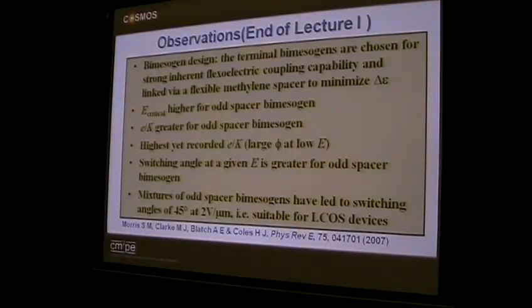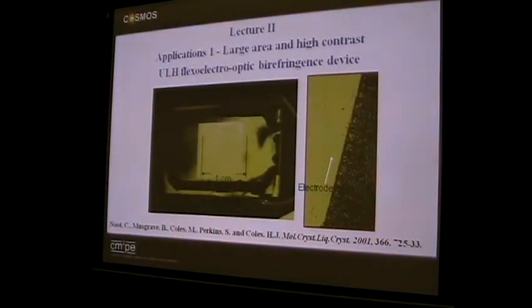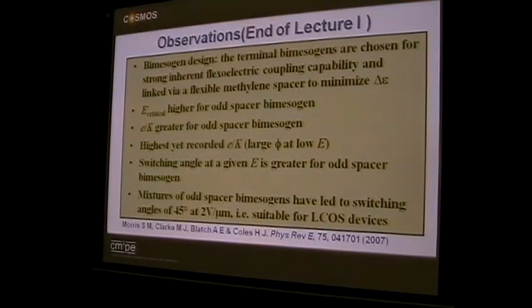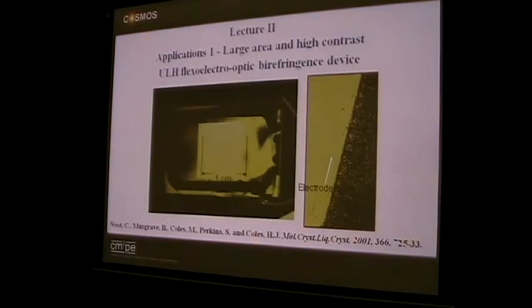Some of the device geometries that are important for what I'm talking about. Firstly, what I want to do is follow on with how you make a device. I said you align the helix in a plane and then you rotate the optic axis. So if I look at an aligned sample, this is the electrode edge here, about a centimeter square, and you'll see that it's quite bright and quite uniform. That's a helix that's lying down in a horizontal plane that's been aligned. That's the electrode edge, so this is the dark region, this is the light region, across the boundary here.